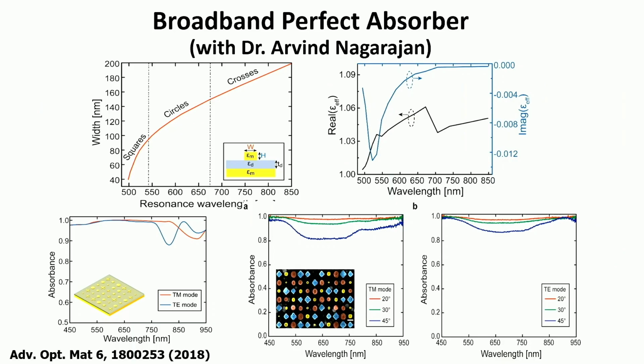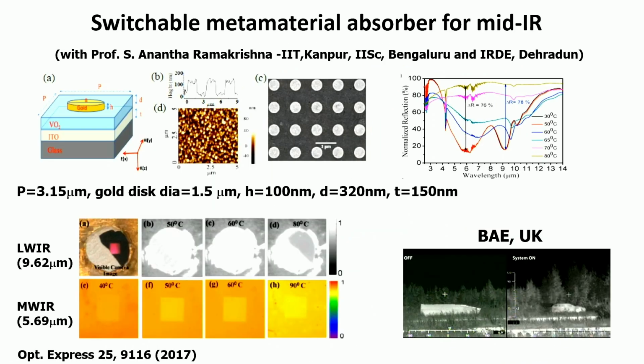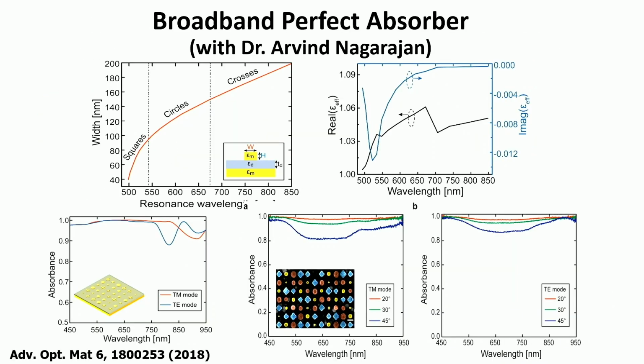What we did is we combined different scattering elements. Depending on the wavelength region, different shapes were taken, and the size of these shapes was designed to be resonant for that particular wavelength region. The squares, circles, and crosses in the top metal layer are patterned as randomly distributed shapes like this. And we showed that we can get about 99.8% absorption over a broad range of say 450 to 950 nanometer wavelength region. So with these randomly distributed scattering elements, we can get a broadened response.